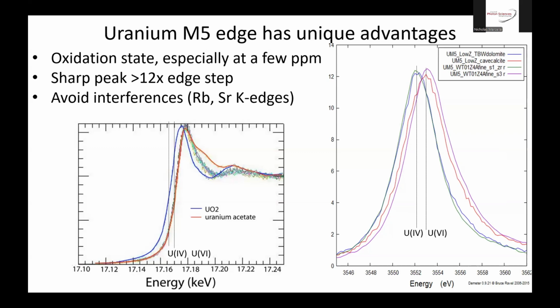Sorry, maybe like give a sense for rating. They range from 30 to, though those samples ranged from 30 to 200 ppm. We've done this measurement down to about 1 ppm. For that you need to measure a few scans. But it's really sensitive. It's such a sharp peak. And even when it's noisy, it's still unmistakable which one it is. That's the beauty of it.